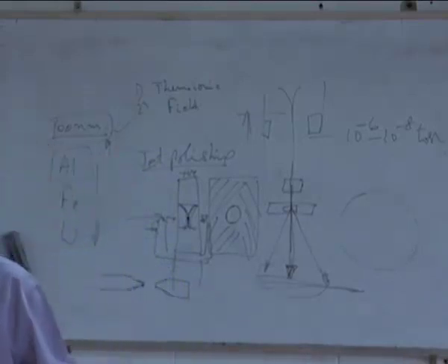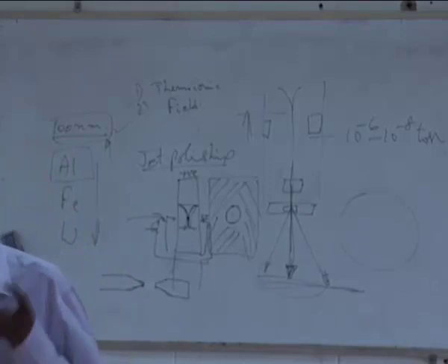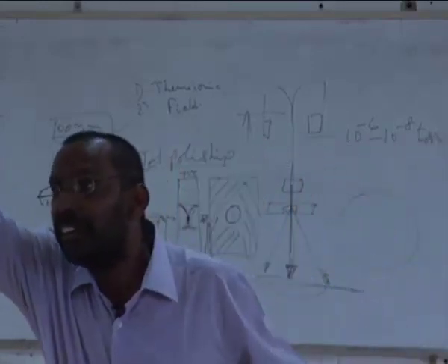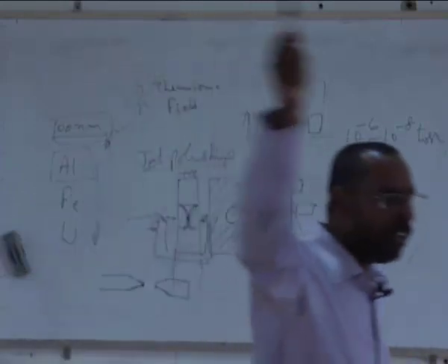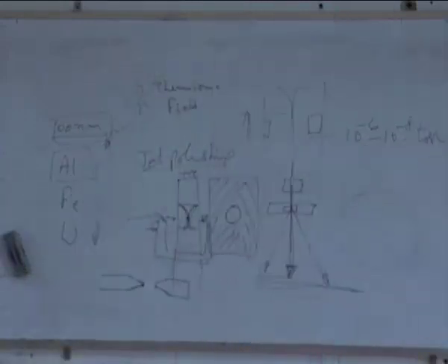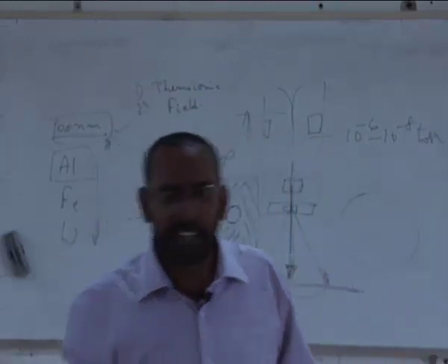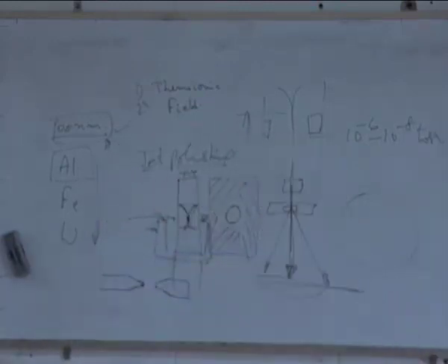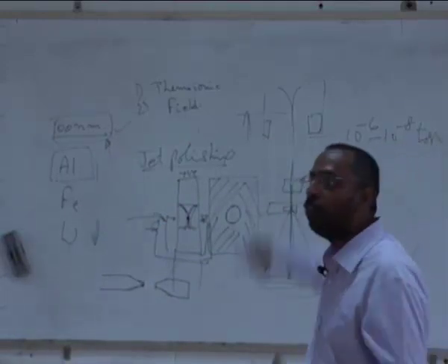But all this is possible only under one condition. What is the condition that is required for doing such kind of electropolishing or jet polishing? Yeah, selective dissolution. Anything more? There has to be a certain property of your sample. Should the sample be non-conducting? The sample should be conducting. If the sample is not conducting, there is no anodic dissolution.